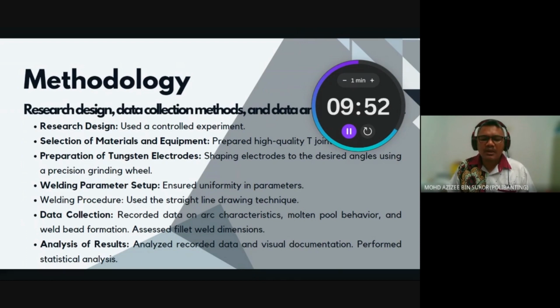The parameter setup: keep parameters like current and gas flow rate constant, only varying tungsten angle. In welding, maintain consistent torch position and speed with the straight line drawing technique. Lastly, the data collection: use cameras for arc and molten pool data, and measure weld dimensions with a welding gauge.